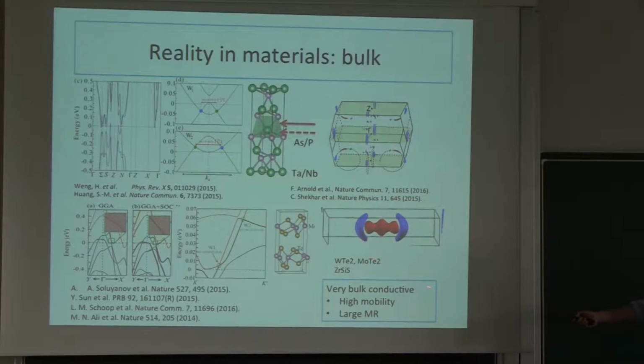Then it's natural we see in experiment this material will be very metallic because of these bulk bands there, and at the same time this is a special dispersion and topological protection, from the Berry curvature, as Lucas said, and gives us the high mobility and a very high magnetoresistance as observed in tantalum arsenide and niobium phosphide, all these materials.